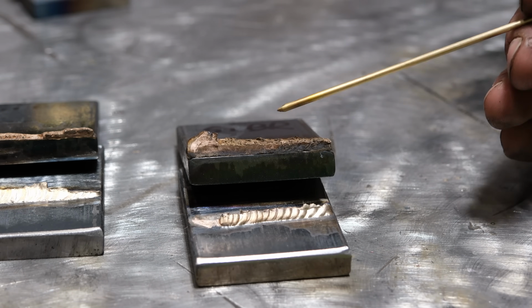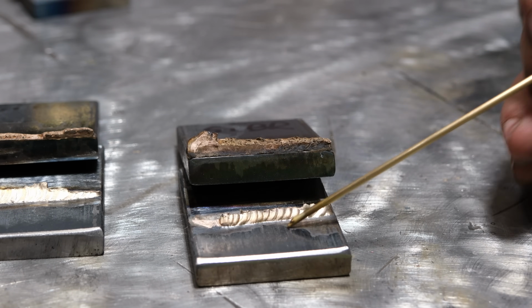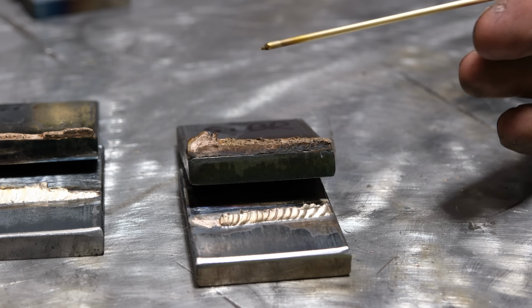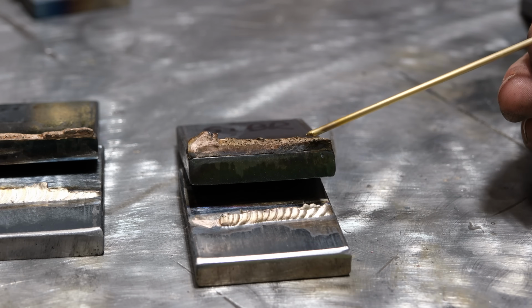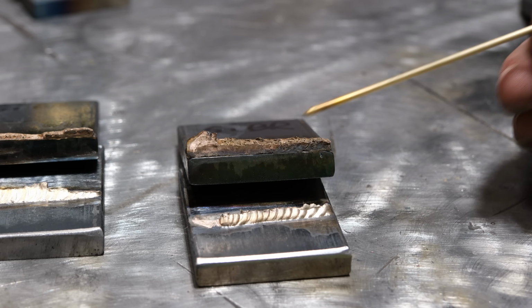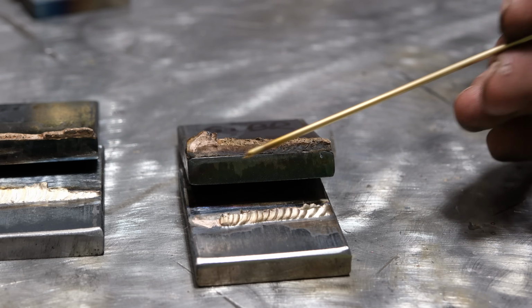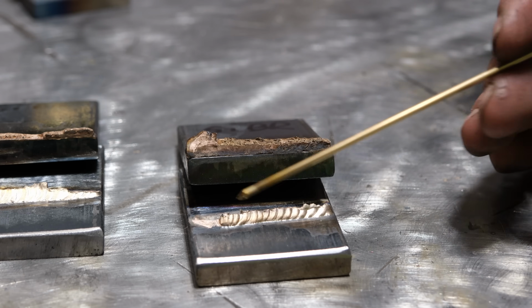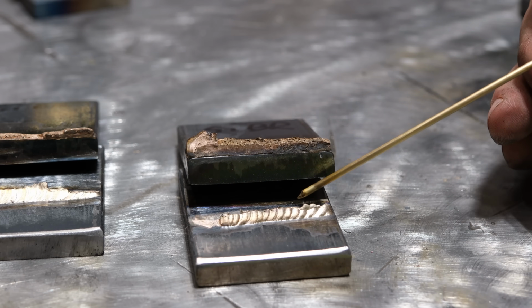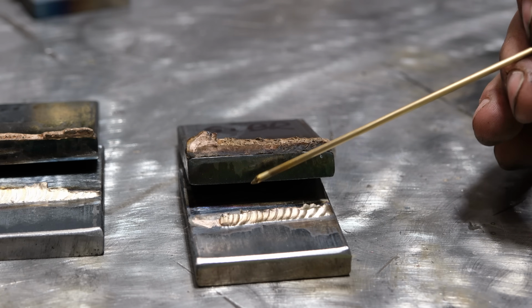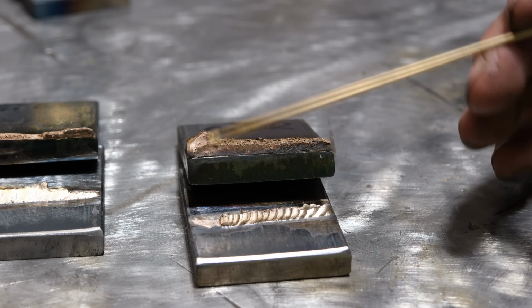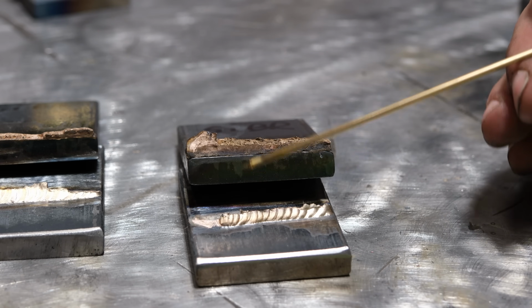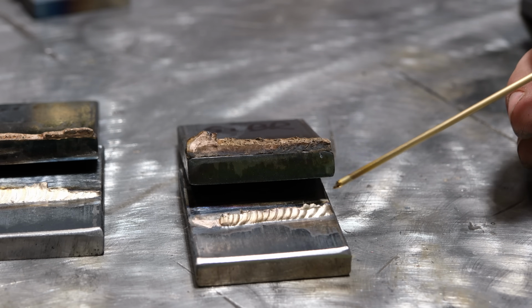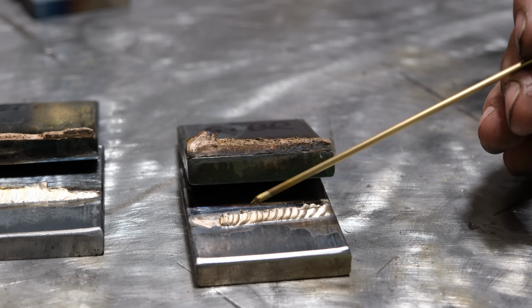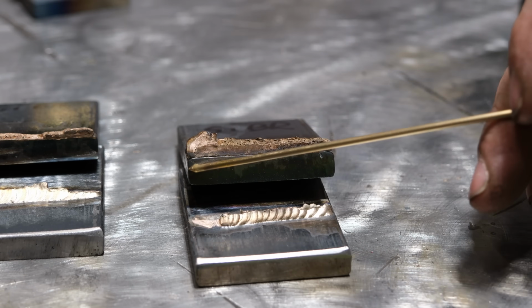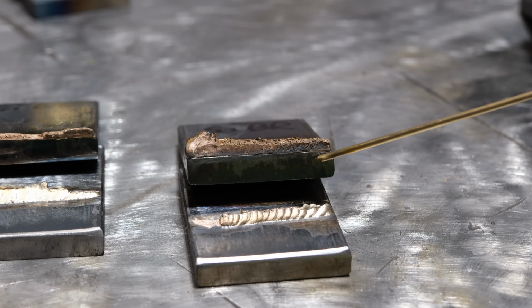Now this multiple pass braze failed even easier than this guy, and I think that comes down to there must have been some shrinkage cracks on this or something, and you really got to watch this stuff. I probably should have slowed down, used a little bit less amperage, and maybe it would have worked, but considering how much this pulled that plate, I just think putting that much braze down on something like this is going to be an issue.